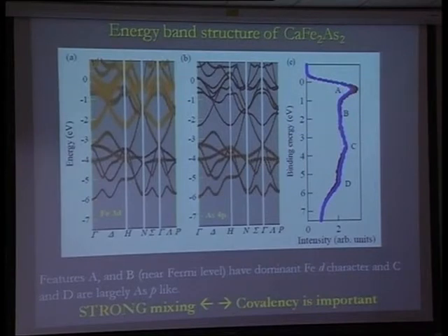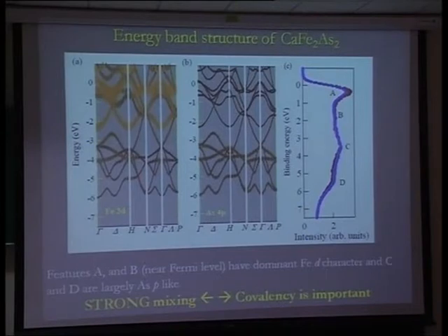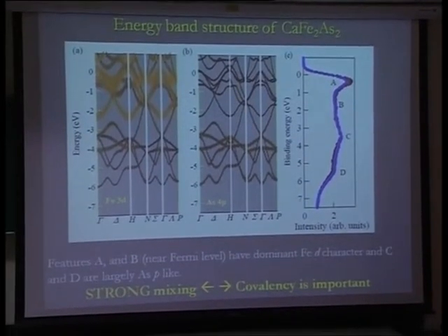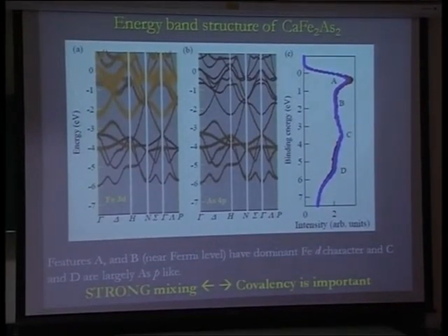Okay. So you can see that close to the Fermi level, the energy bands have strong iron 3D character, but it's finite at higher binding energy too. And here you can see the energy bands in this energy region have strong arsenic 4P character. So this immediately shows, just by looking at them, that there is a strong mixing of iron 3D and arsenic 4P. Okay? So the covalency is really very, very strong in this material. So that's the thing which you can see.